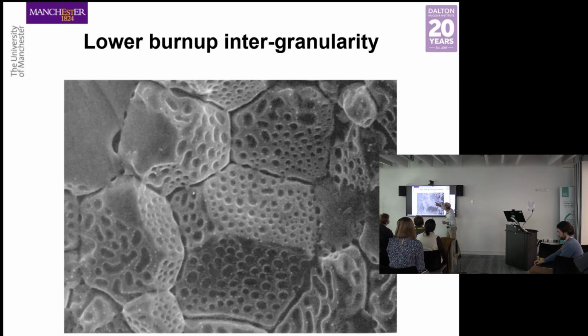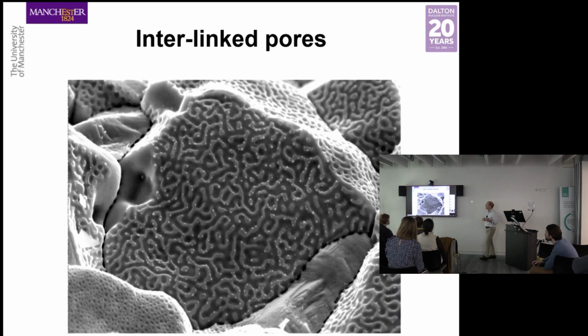You can see those long cigar-shaped gas bubbles at the grain edges. They haven't actually joined together yet, but that's where they're going. They're joining together. We call it interlinking. And eventually we get fully interlinked pores where it's a little bit like a maze, but you can imagine if you were a gas atom that found its way to a grain edge, then the grain edges are all pretty much open. The gas vents. It's released into the voidage inside the fuel rod.